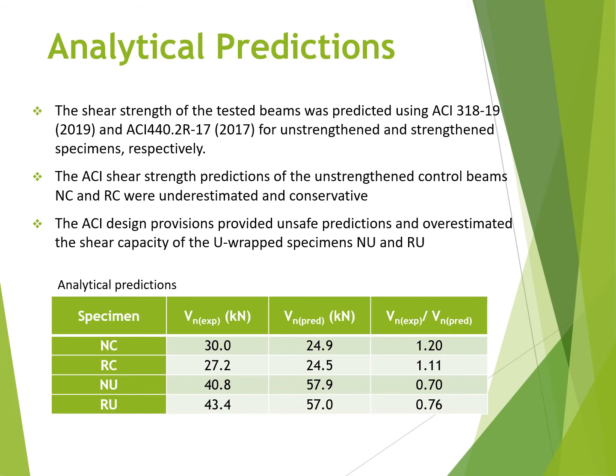The shear strength of the tested beams was predicted using ACI 318 for the unstrengthened beams and ACI 440.2R for the strengthened beams. So you can see here from the table, this is the experimental shear capacity, this is the calculated predicted shear capacity, and this is the ratio of the experimental to predicted. As you can see from the table, the shear strength predictions of the control specimens were underestimated and conservative, with the ratio of experimental to predicted being greater than 1.